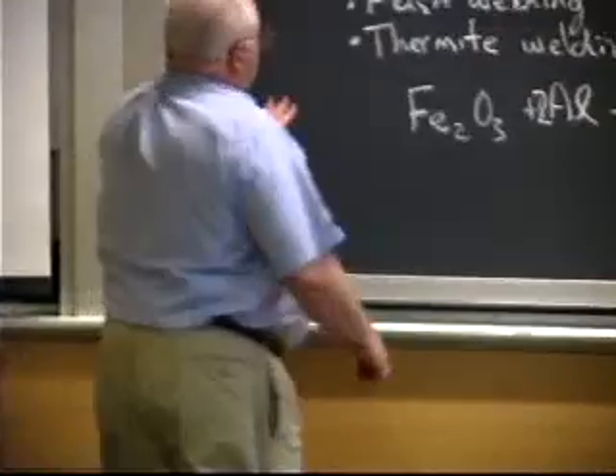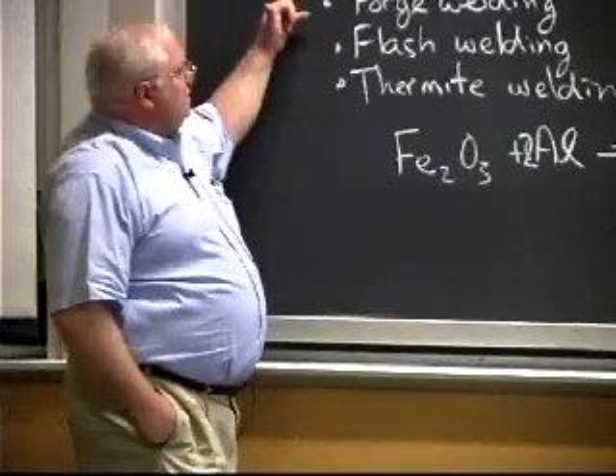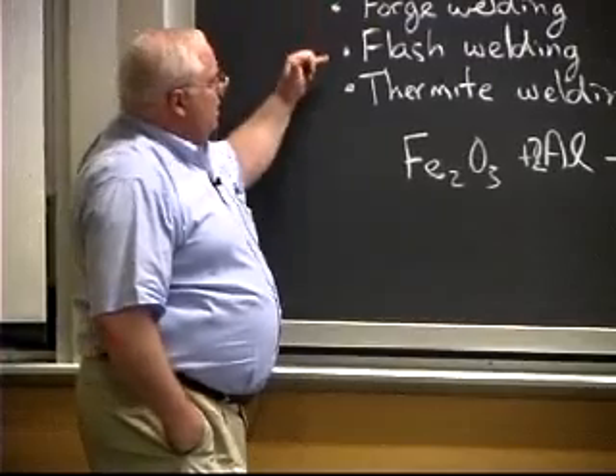You want to run continuous steel sheets through the steel mill for rolling or plating or whatever you're going to do to the steel, and you bring the sheets together with a great big flash welder, and it might be 8 feet wide, and here you may need that magnetic field to move the arc back and forth across that sheet. You bring the two sheets together, you start a little arc, you pull it apart, let the arc melt the edges, keep on pushing it closer and closer, and finally when you're ready, you slam it together and make your weld. Very expensive equipment, fast; very cheap equipment, slow.